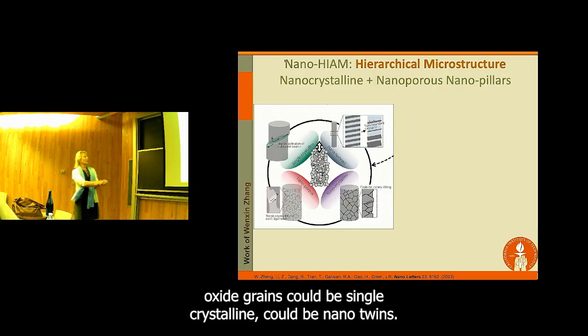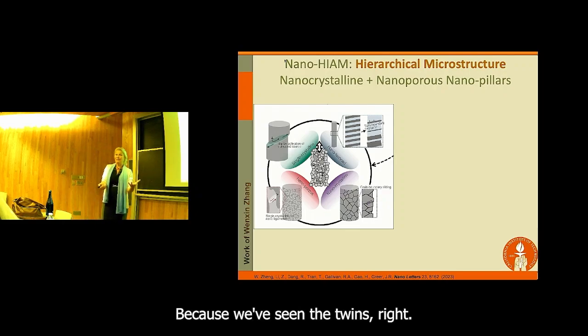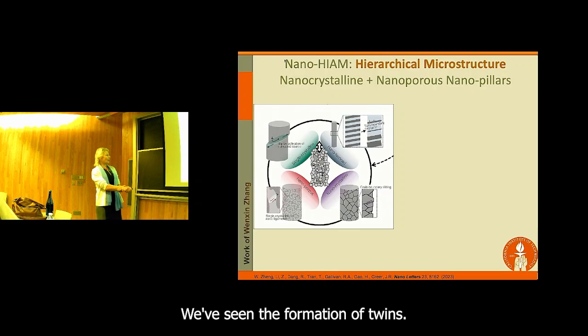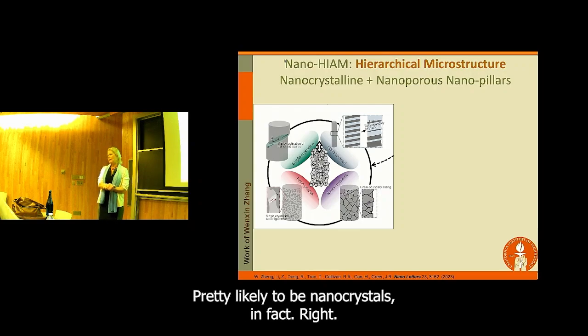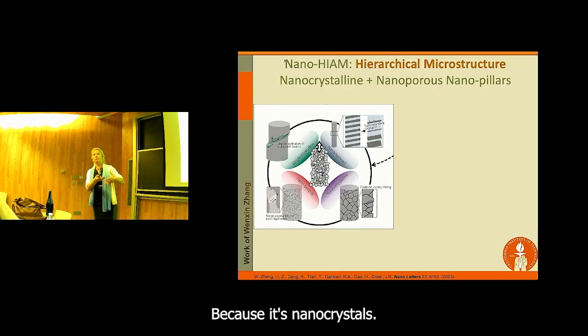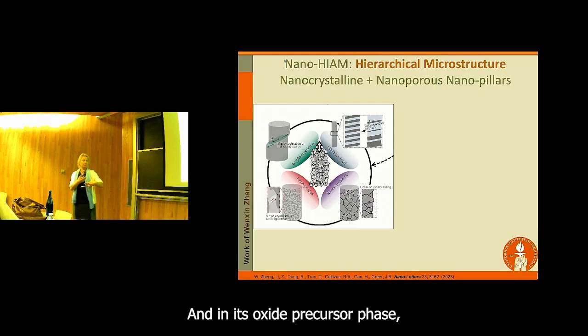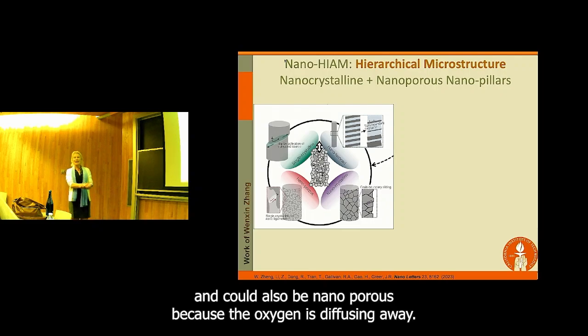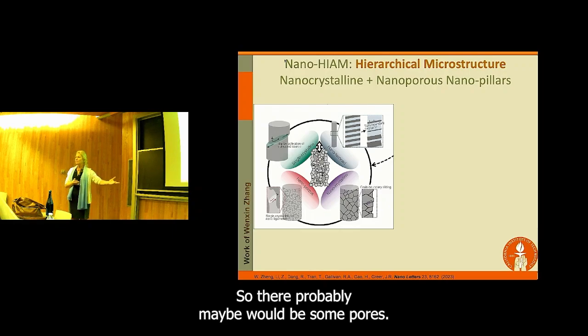Could be single crystalline. Could be nano-twinned, because we've seen the formation of twins. Could be nanocrystalline, pretty likely to be nanocrystalline in fact, because it's nanocrystalline in its oxide precursor phase. And could also be nanoporous, because the oxygen is diffusing away, so there would probably be some pores.